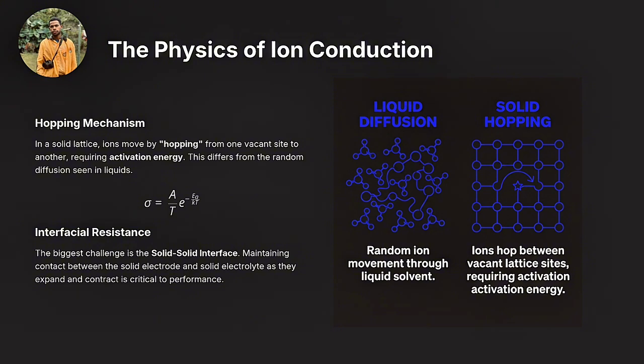However, there is a huge challenge: the solid interface. This is where the solid electrode meets the solid electrolyte. In liquid systems, electrodes and electrolyte naturally conform to each other. But in solid systems, contact is imperfect. As batteries charge and discharge, the electrode expands and contracts. If contact is lost, you get interfacial resistance. It simply means that if the contact is lost, you get interfacial resistance, wasted energy and heat.